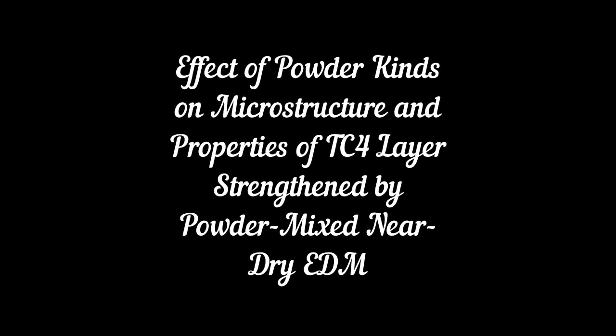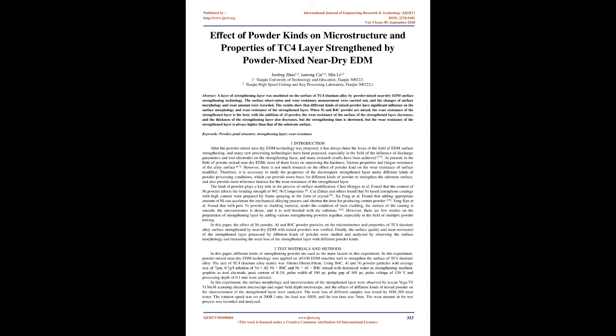Effect of powder kinds on microstructure and properties of TC4 layer strengthened by powder mixed near dry EDM. A strengthening layer was machined on the surface of TC4 titanium alloy by powder mixed near dry EDM surface strengthening technology. The surface observation and wear resistance measurement were carried out, and the changes of surface morphology and wear amount were recorded. The results show that different kinds of mixed powder have significant influence on the surface morphology and wear resistance of the strengthened layer.